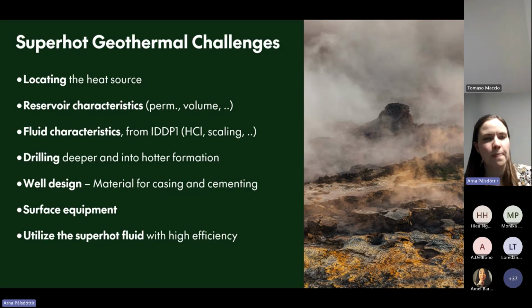But there's a lot of challenges when we look at Superhot geothermal. Firstly, the challenge is locating the heat source. And that, fortunately, is something that we have worked on through the years. We have a lot of experience in these areas that we operate in, and we believe we have a pretty good idea of a number of locations where we can locate these Superhot geothermal resources. Once we have drilled and found that resource, there are reservoir characteristics that are a challenge. So what's the volume of the resource that we actually reach with the wells that we drill? And what's the permeability? Are we actually going to produce fluids from this? And then